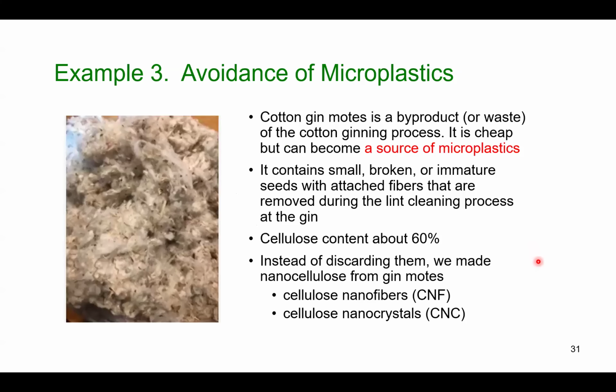Now, a third example is the avoidance of microplastics. So cotton gin motes is a byproduct, a waste product of the cotton ginning process. It is very cheap, but can become a source of microplastics because these are discarded. Once it's not being used, you discard it and it gets in the water stream, gets in the air, so it can be a source of microplastics. It contains small broken immature seeds with fibers, and the cellulose content is about 60%.